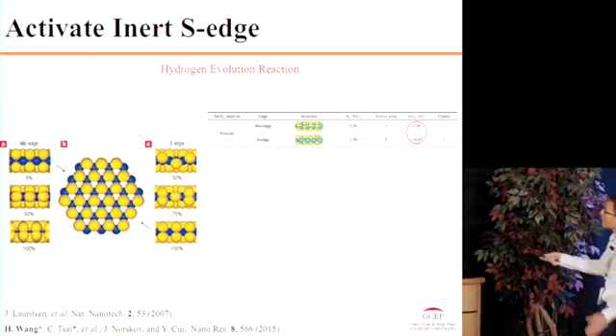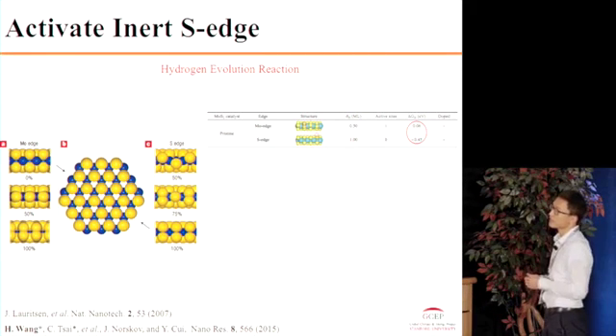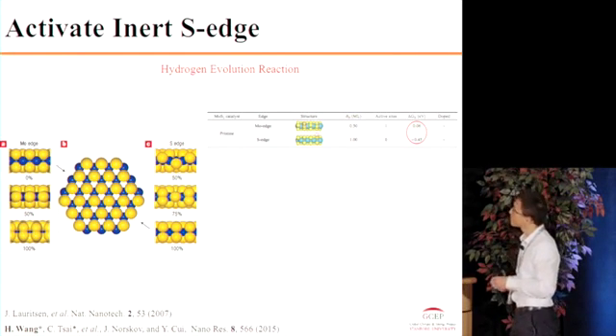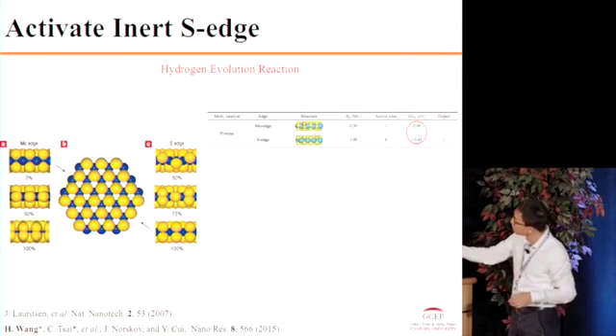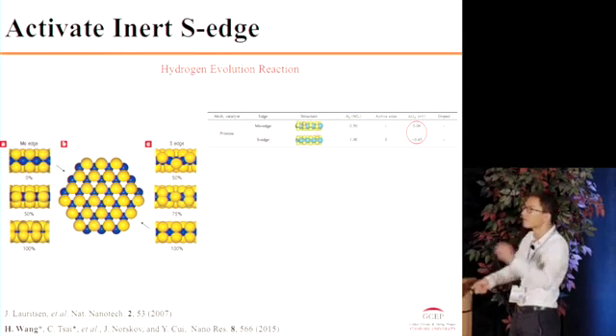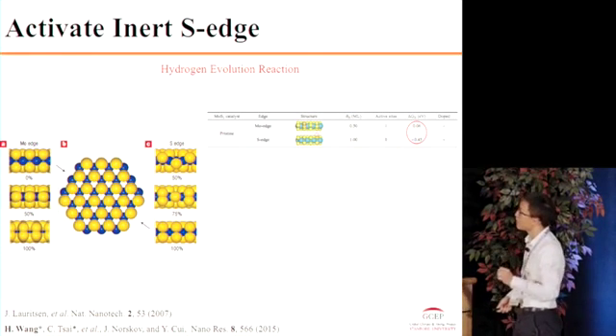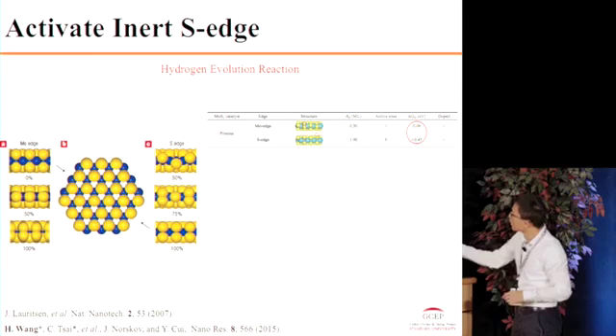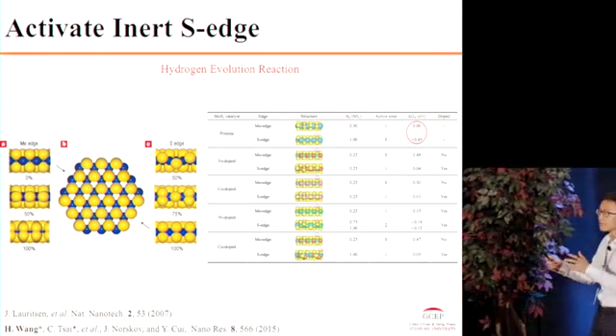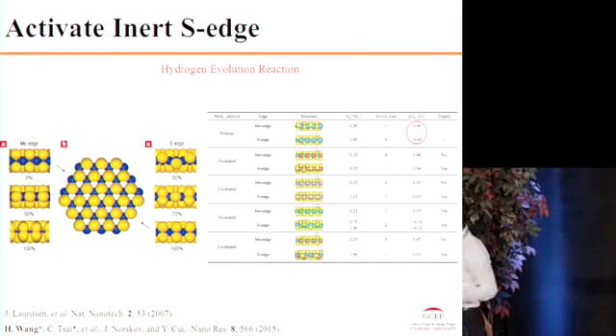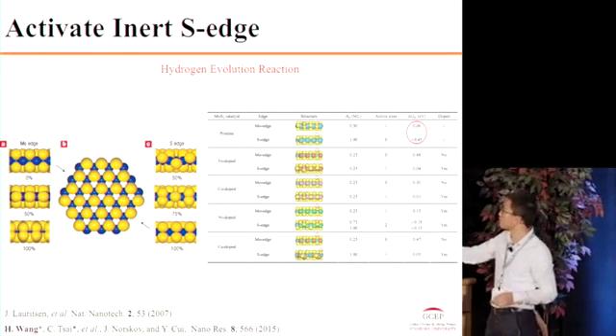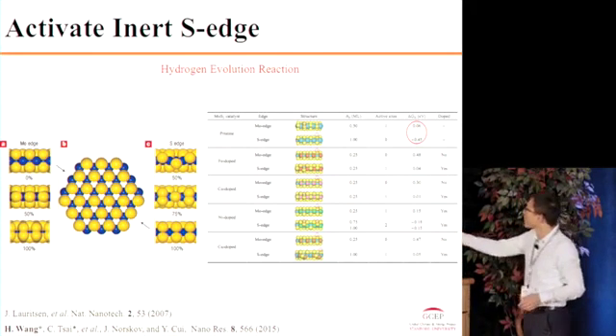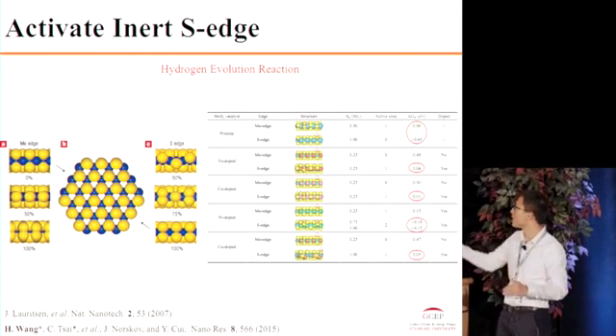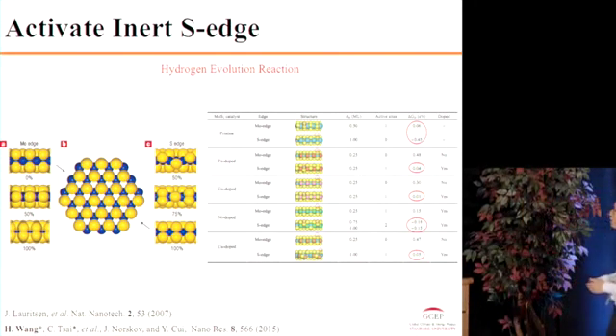If we look deeper into the edge sites, we realize that there are two types of edge sites. One is the molybdenum edge site, which is the active site for hydrogen evolution, and the other is the sulfur edge site. With the help of Professor Jens Nørskov, from the theoretical simulation we realized that the sulfur edge site binds the hydrogen too strongly, so it is not active for the hydrogen evolution reaction. The way we want to activate this half of the sites is to dope the edge site with transition metals, including nickel, iron, and cobalt. We can see that the free energy decreases very much, activating the other half of the edge sites.